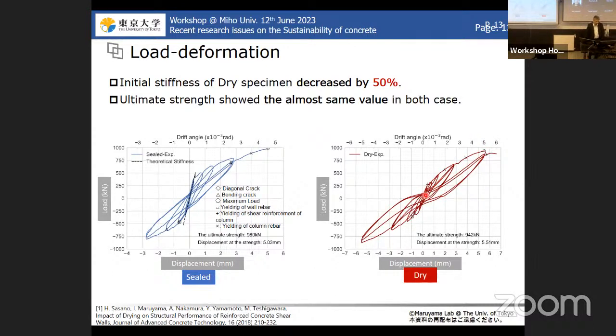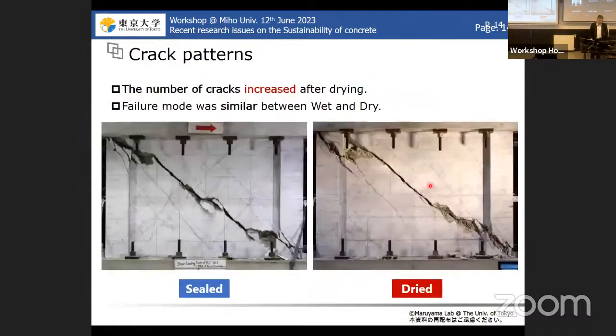And now this is a proof that the stiffness of the structure can be reduced just by drying. And the decrease in the stiffness of the wall becomes 50%. So this is a very big impact. The failure mode is quite close, as you see, so very similar shear failure.